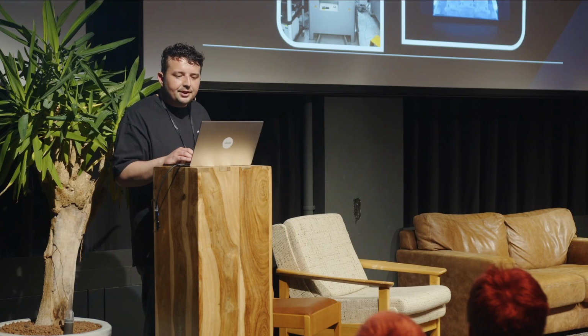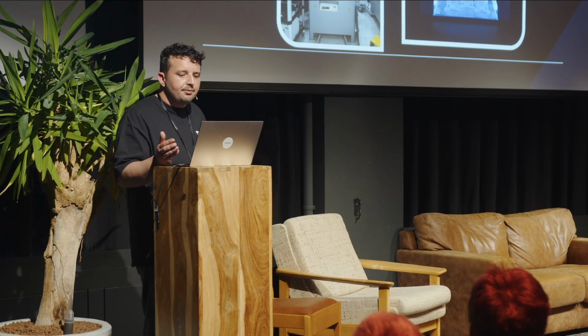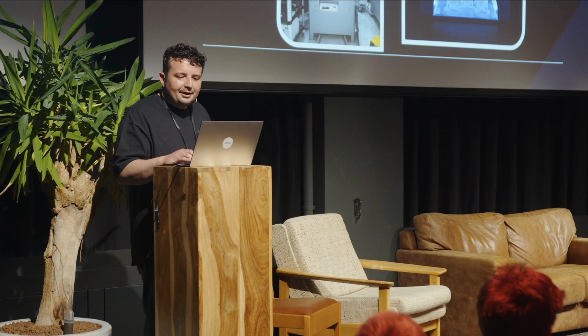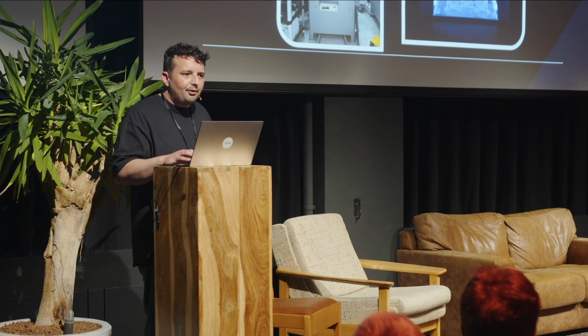Most metal builds need to be put in a furnace after printing to relieve stresses. And if you're post-curing your resin prints, that's basically stress-relieving metal parts, just with UV instead of an 800-degree furnace. And it's the same way of thinking, just on a different scale.